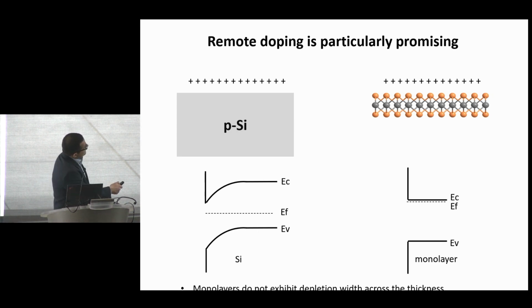But in the case of a monolayer, there is no depletion. There is no depletion depth. There is going to be no band bending going from top to the bottom. You cannot drop potential across the thickness of the semiconductor. So the bands will be flat if it's just a monolayer. If it's a bilayer, you can start to get some band bending, and as you add more and more layers, you will then get closer and closer to the bulk case.